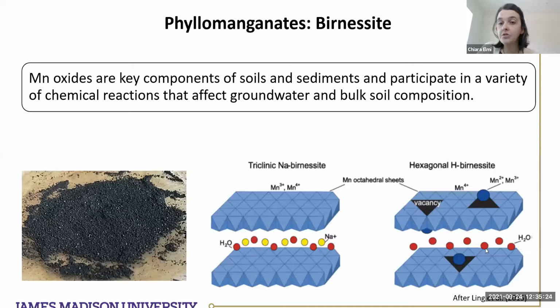So I studied these two structures. One is the triclinic, which is more stable at ambient condition, and the hexagonal H birnessite, which loses the cation in the interlayer, and there's a generation of vacancies that can be replaced with manganese 2+. Manganese 2+ is generally more stable in aqueous solution. So most of the time the substitution is also with manganese 3+. This happens when there's a change in pH in the solution. In a more acidic condition, we can have this change in the structure.